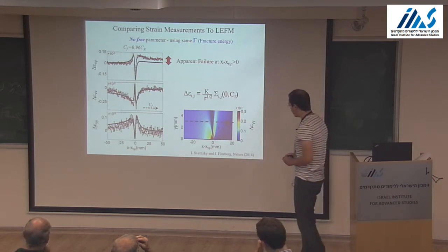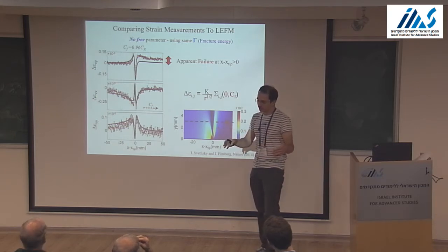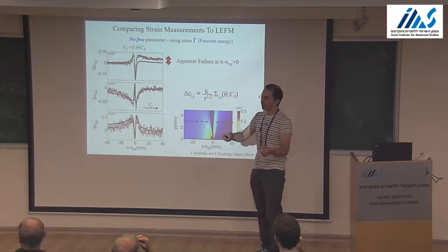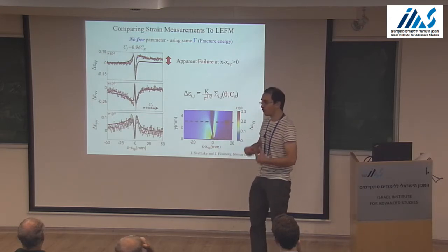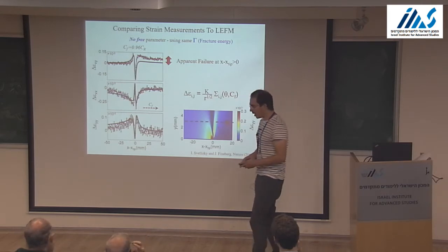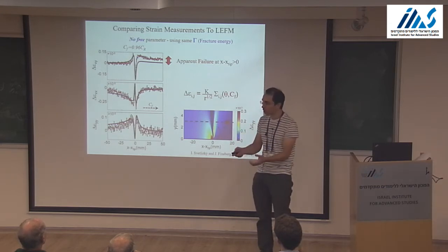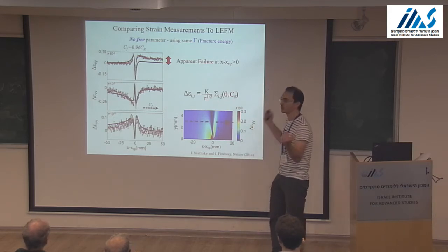Essentially, we believe that on these length scales, it can be considered. The acceleration is slow enough for all the fields up to 3 millimeters to adjust, and we see just locally the stationary solution. In fact, the equation of motion by Freund was also built upon superposition of stationary solutions. Mathematically, it can be allowed if you always go close enough to the crack tip. Even at high velocity, high acceleration, you can go even closer to the crack tip where you will have the K dominance, which is always a stationary solution. In practice, it works.